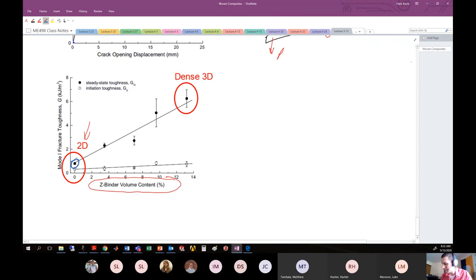When you're incorporating these through thickness Z-toes, it's insane. All right, this is crazy, how much increase in toughness that you're getting, all the way up to like 6,000 joules per meter squared. You ain't making any 2D composites with 6,000 joules per meter squared toughness, I tell you that. All right, take that to the bank. I don't care if you incorporate thermoplastics. I don't care if you incorporate toughening agents. Even with stitching, you might not even be able to get that high. This is just an insane value, all right? That's bordering on what aluminum would be, all right?